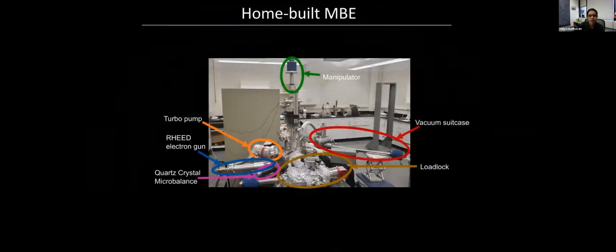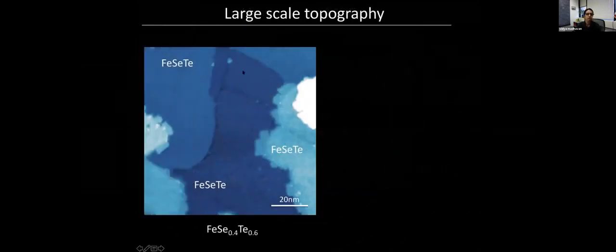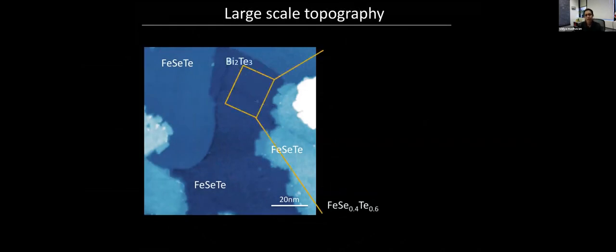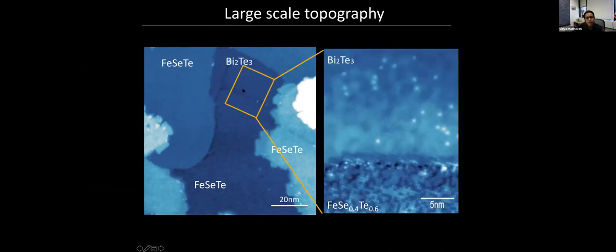So we wanted to try to grow monolayers of FeSeTe on bismuth telluride for various reasons. I don't know if I'm going to have time to go through this whole thing, but let me show you a few slides because this is very interesting. We used our MBE system to grow FeSeTe on bismuth telluride. So here's bismuth telluride, and here's FeSeTe. You can see very clearly the hexagonal lattice associated with bismuth telluride, and this is one monolayer of FeSeTe.